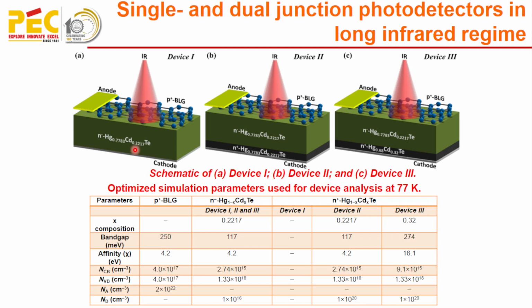So in the case of device 3, it has the dual heterojunction. One is between the bilayer graphene and mercury cadmium telluride, and one is between the mercury cadmium telluride and the mercury cadmium telluride with another x composition. So the device has been characterized in terms of various electrical and optical parameters, and it was found that the dual heterojunction shows better performance as it has minimum thermal generation and parasitic impedance, and the alloy composition of this